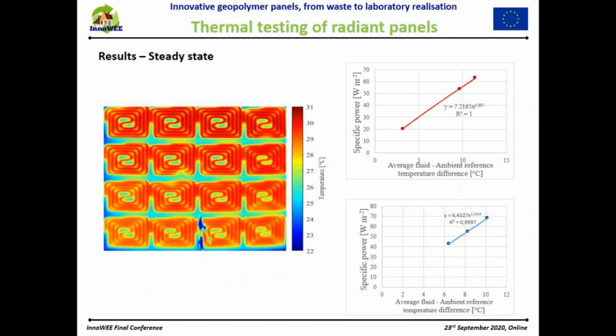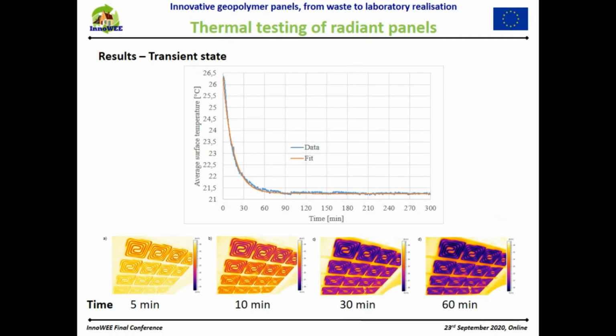And these panels are very homogeneous, and as expected from the numerical simulation, the thermal output is higher than a traditional commercial solution with plasterboard finishing. In transient mode, we display the surface temperature after turning on the system, and you can see images at 5, 10, 30, 60 minutes after the start, and the curve of the average surface temperature shows that these systems are fast, with a time constant that is around 15 minutes.